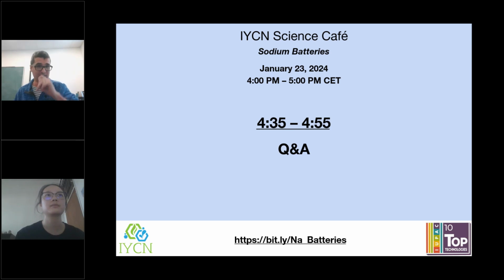On the cathode side, structures that work really well with lithium sometimes aren't even stable. So lithium cobalt oxide is the historical, the first cathode used for lithium ion batteries. You can't make that structure with all the sodium in it. You have to make it with a fraction of the sodium because it doesn't want to go into that environment. It's an octahedral environment that lithium goes into.